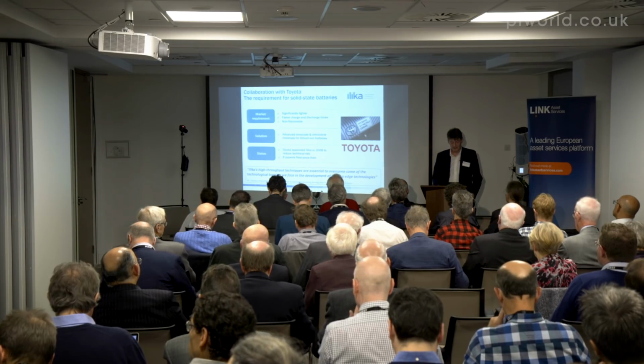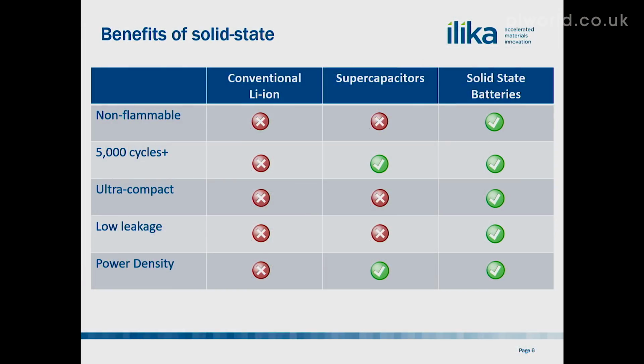In the course of doing that, we also actually identified that there were some other advantages to going to a solid-state device, and they're summarized on this slide here. So first of all, you find that actually the cells can be cycled for a greater number of charge and discharge cycles, which effectively means that the battery has got a longer lifetime. So, typically a standard lithium-ion cell, you can charge and discharge about 1,000 times before the performance of the cell starts to drop off. You know that from your ownership of a mobile phone. So after a couple of years, actually the battery starts to die and you don't get quite as much lifetime out of a single charge.